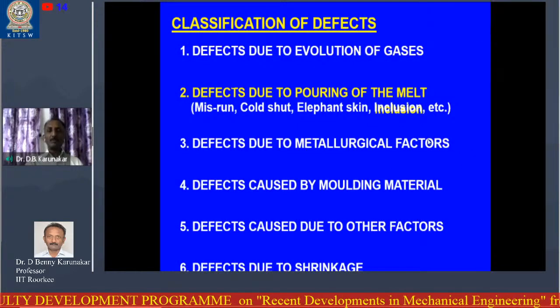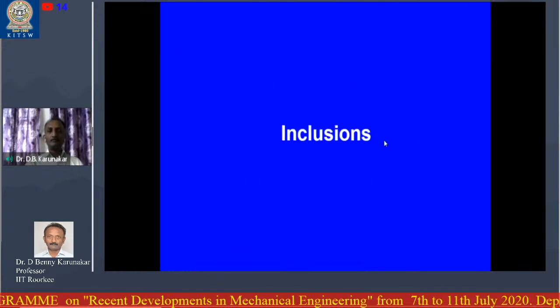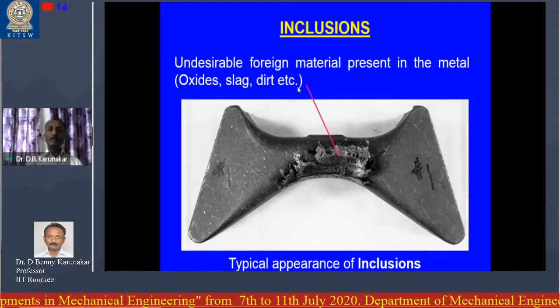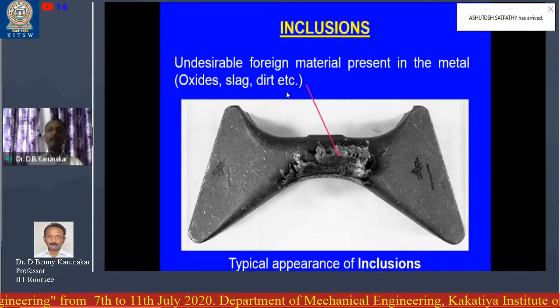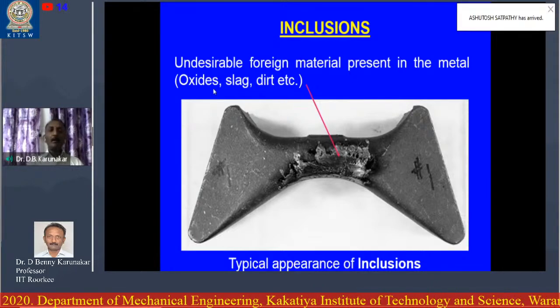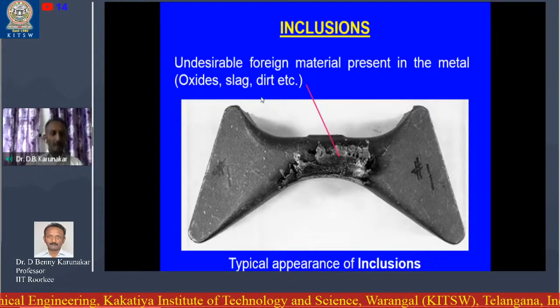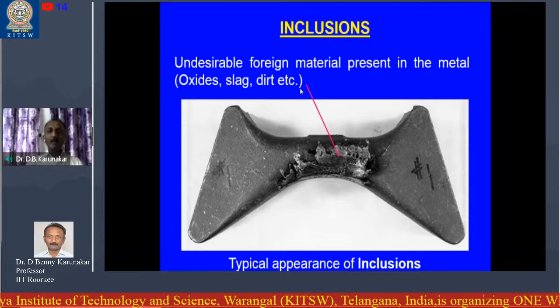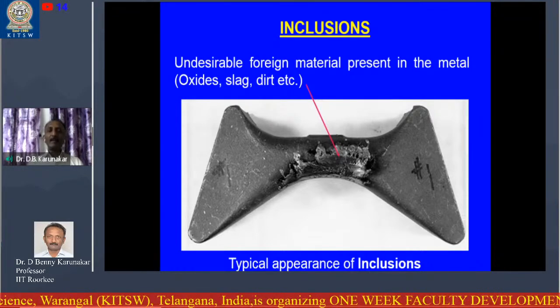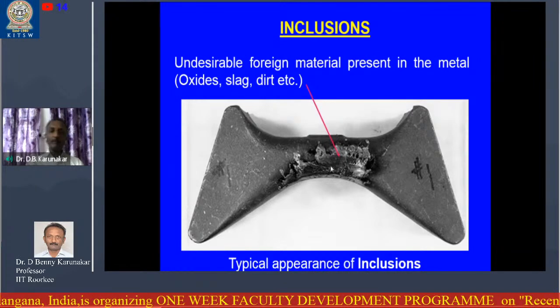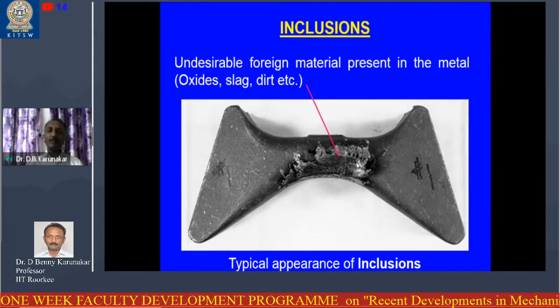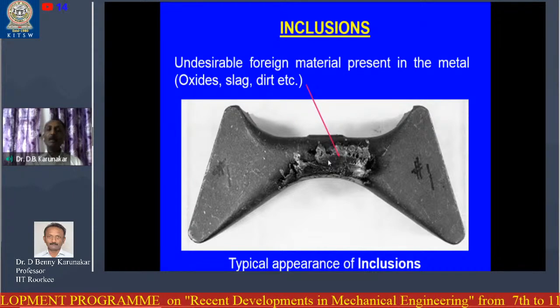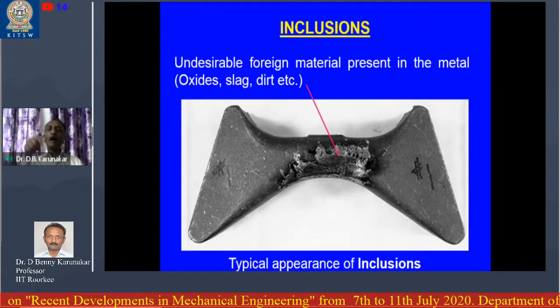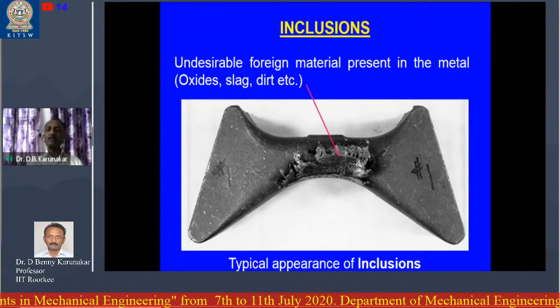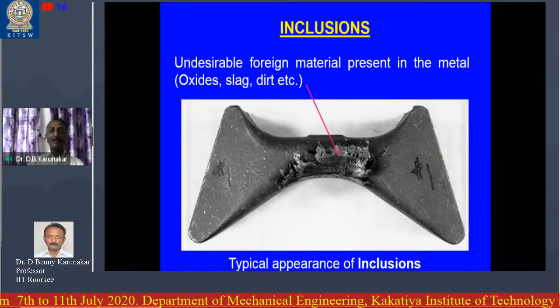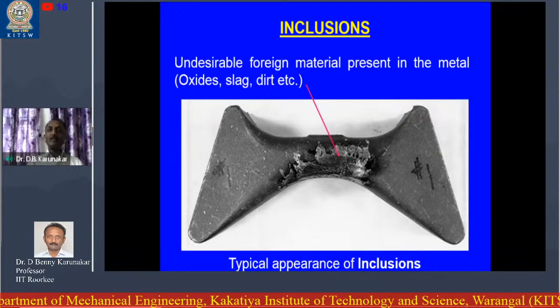Next one, inclusions. Now, what is this inclusion? Undesirable foreign material present in the metal - those foreign materials could be oxides, slags, or dirt. They come along with the molten metal, enter into the cavity, and after the casting is solidified, they are deposited on the surface of the casting like this. These will be peeled off, and ultimately we see a depression on the casting or a discontinuity on the casting. That is the final result of this inclusion.